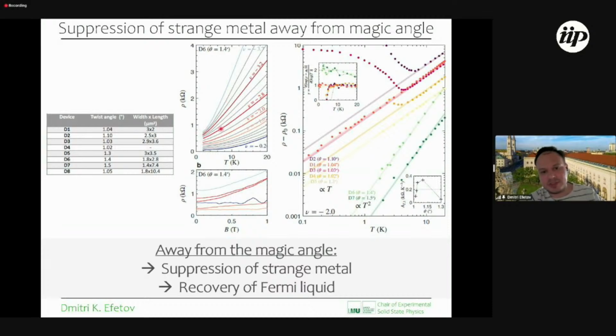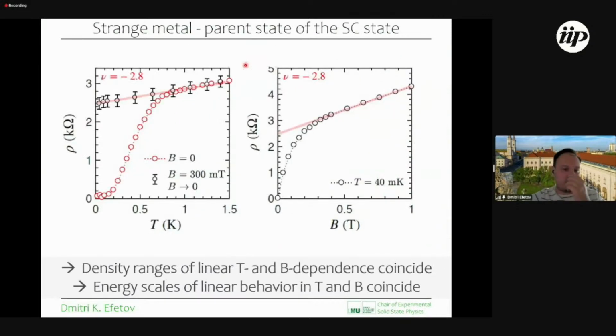If you look at the temperature dependencies of these curves, they all look like power law behavior with a linear temperature dependence at high temperatures. So really, it looks like single layer graphene, and we can strongly distinguish these phases from what we observe at magic angle. And one thing which is also interesting, as I mentioned, is that we also observed a superconducting phase in this phase diagram. So of course, we would like to see whether the strange metal phase and the superconducting phase are also overlapping. And for this, what we could do is measure the typical resistance as a function of temperature in the superconducting state. So we would get this transition temperature of around 500 millikelvin here, where the resistance basically drops to 0.